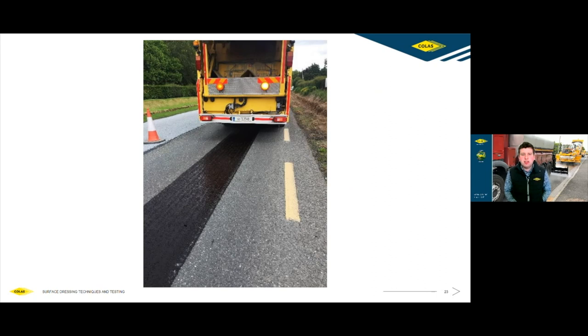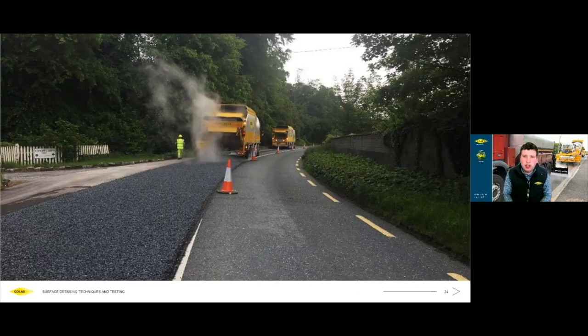People might be asking about deformation underneath the road. The way to get the best surface dressing is to make sure the layer under the road is uniform. This can be done by doing a pad coat if needed — a light spray of emulsion with a 6mm chip. Here we had fattening in the two wheel tracks and in the middle of the road it was more open. We decided to spray just the middle of the road with a layer of binder. On the day we had two OB Combi units. We sprayed down the middle of the road with a slight bit of binder and then came across with a single surface dressing, knowing we had a uniform layer to spray on, and we got a very good surface dressing after that.